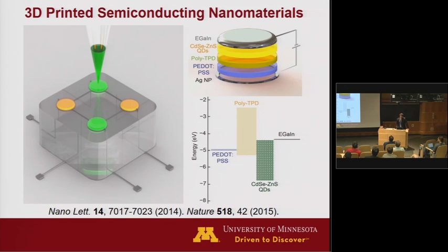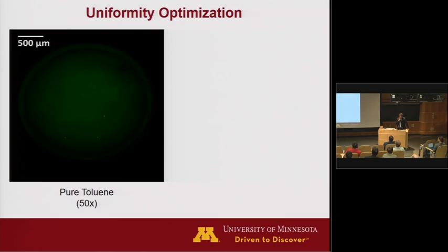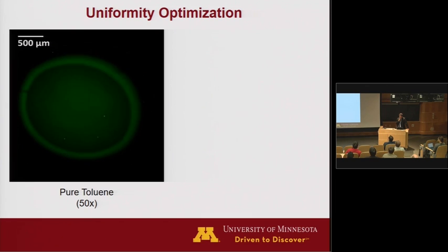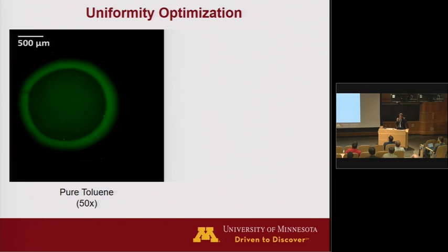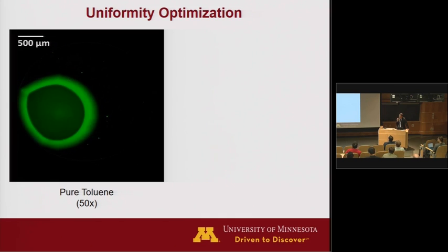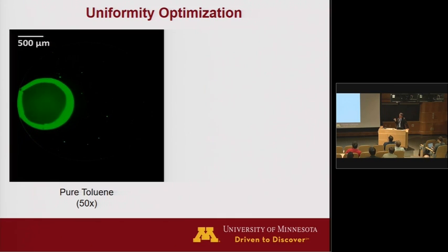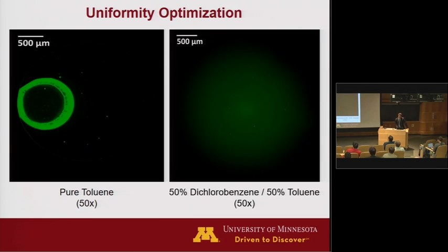This doesn't even include the biological, but there's some tricks to doing this. I should mention that to 3D print a semiconducting ink, you have to be very careful about your ink formulation, because if you just deposit a droplet of particles on a substrate, it'll dry and all the particles will spit out into this coffee ring. So what we do is we use tricks from chemistry using low surface tension co-solvents. As the droplet dries, it actually creates a uniform distribution of these particles throughout the droplet. And that gives us uniform device properties.